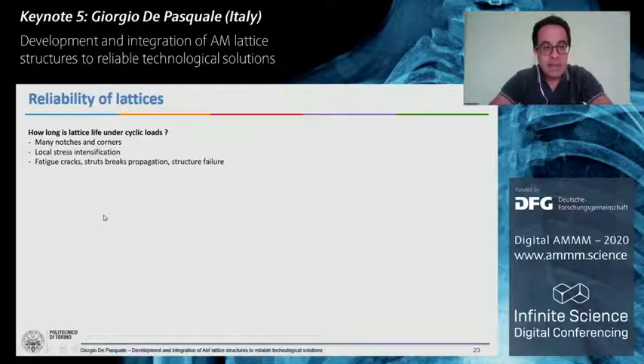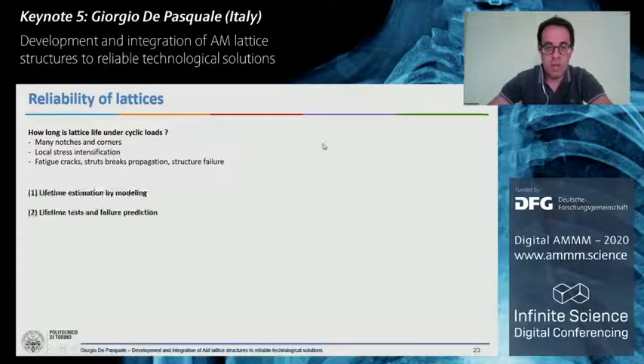What about the reliability of lattices? This is a quite important topic for mechanical design, because a structure that is strong in static conditions may be very unreliable under cyclic loads. So we need to understand what happens if you apply cyclic loads to the lattice structure. We have a lot of notches, a lot of corners that are potential points of initiation of fatigue cracks that may induce breaking in a very short time. We have 2 approaches to investigate this. We can estimate the lifetime of our component by modeling or by tests and failure predictions.